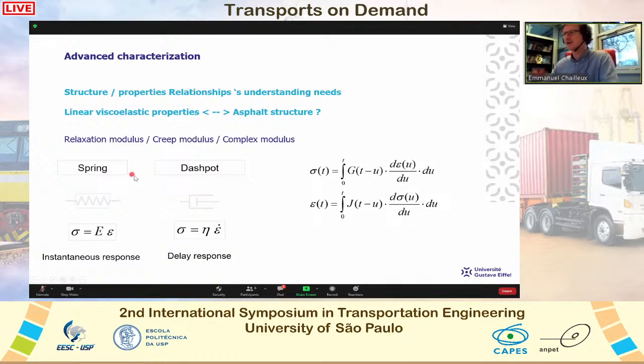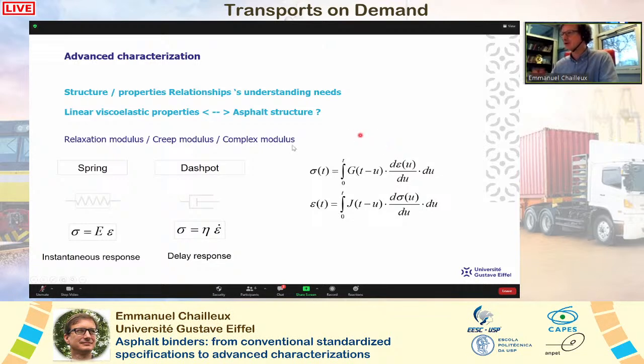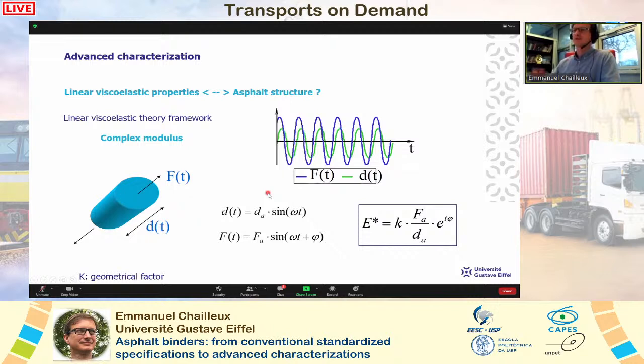And the linear viscoelastic theory says that we can define the relaxation modulus like that in a hereditary integral, where you have the stress and the rate of strain, or, the opposite, the creep modulus, where you have the strain and the rate of stress, where you can calculate this strain using a hereditary integral. But I prefer to speak about what we call the complex modulus, which is one of the properties we can measure using the linear viscoelastic theory framework.